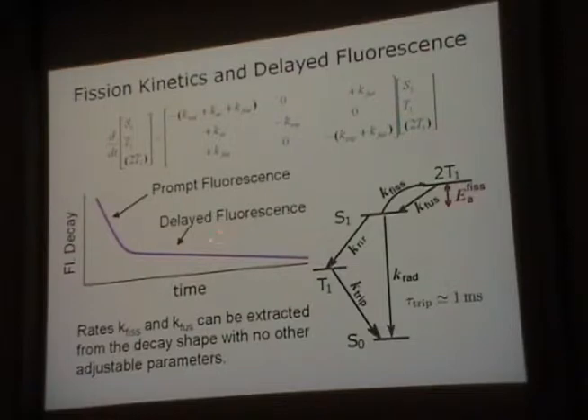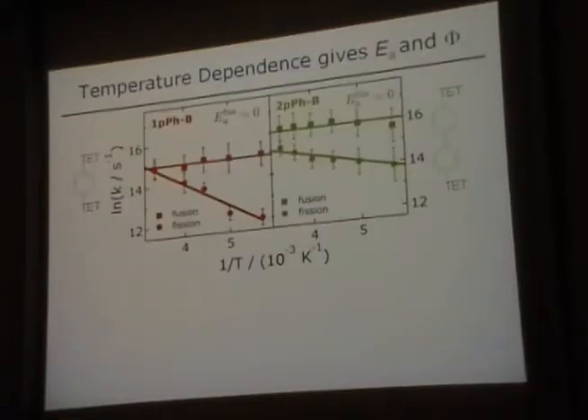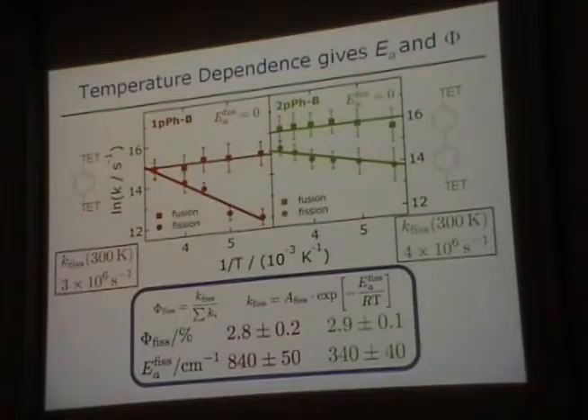Basically, K fission determines when you sort of increase the decay rate, and then where this break is, basically the yield of the triplets, and then K fusion is the lifetime of the delayed fluorescence. That's the dominant channel that you lose triplets from, is that fusion. It turns out that the triplet relaxation rate is about a millisecond in solution. So we're pretty safe in terms of analyzing the kinetics. We can analyze the heck out of the kinetics because we're physical chemists, so that's what we do.